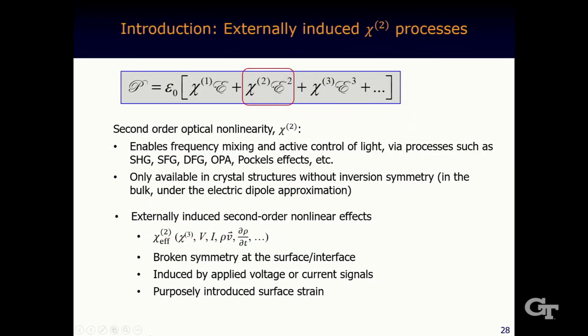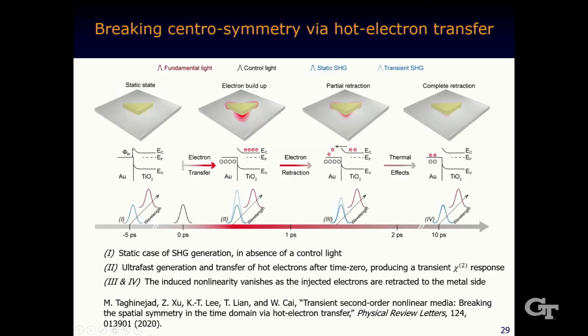Without hot electron transport, the response would be much slower and also much weaker. And now for the next, I have only almost 5 minutes left, so I'm going to skip a lot of slides just to give you some very quick flavor of how it looks. We can also use the hot electron to enable second-order nonlinear optical response. Basically, in a material initially with a zero chi-2 response, we temporarily use hot electrons to convert that into an effective second-order nonlinear medium, and then modify the harmonic generation and optical rectification and so on in the structure.